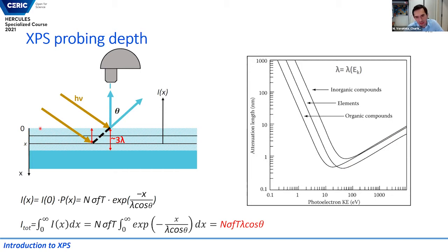So for photoelectron spectroscopy in the presence of gases, the photon energy is quite a sensitive parameter. And usually the best is to work with photoelectrons in the region of more surface sensitivity, so from 10 to 100 eV or so.